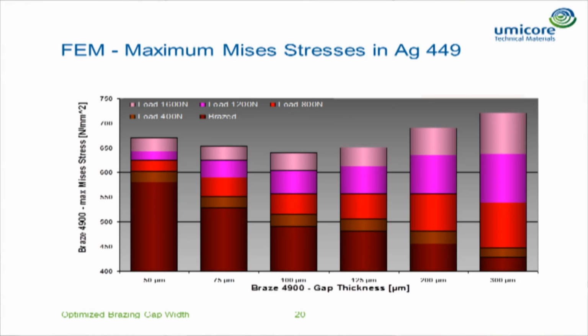When we now look at the Mises stresses in the brazing alloy layer, this is quite interesting. After brazing, we can see that the stresses in the thin layers are very high, and then they are decreasing. This is similar to what we found with the small layers. We could see that the failure was mainly on the steel side. And then we add the load, and again we could see that the stresses inside the brazing alloy layer had a minimum around 100 microns. And this is similar to our 4-point bending tests.